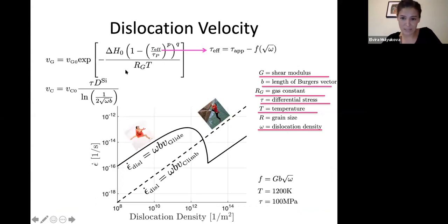Quantitatively, and you don't need to remember those equations, the most important part I want to point out here is that this is our glide velocity. And again, just to emphasize, both of these processes are thermally activated. So to move a dislocation, both in glide or by climb, you need thermal activation of smaller scale defects along the dislocations. However, glide in its plane is strongly stress dependent. And it's not just the applied stress, the stress that you're applying to deform the rock, but it is also the effective stress, meaning the applied stress and the internal stress that is due to the presence of other dislocations.